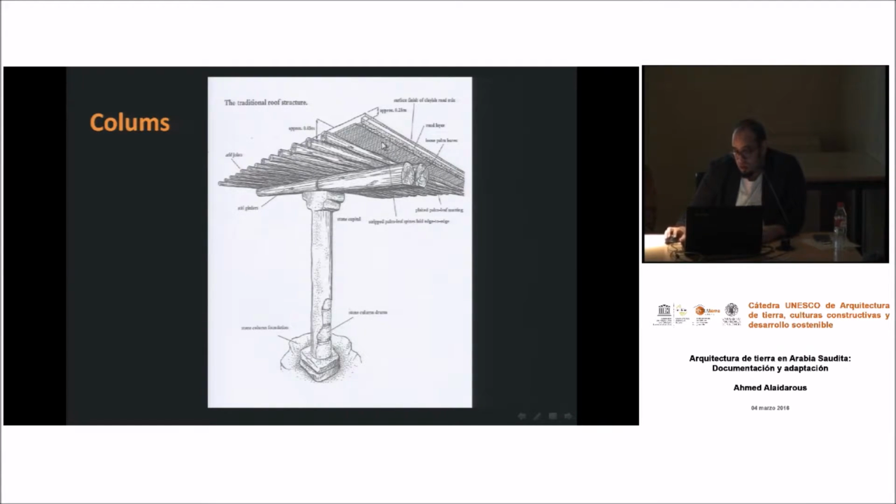Joist, yeah. And above it, the next level, which is palm leaf, put above the joist, and after that, a layer of the mud render mixture of 15 centimeters, and keep it to dry for 10 days, and put one more level of mud.